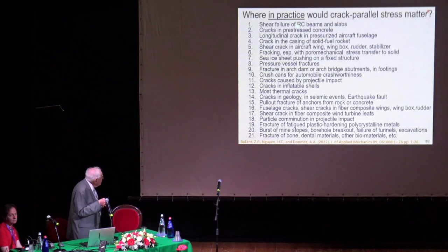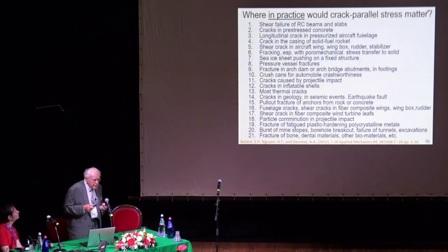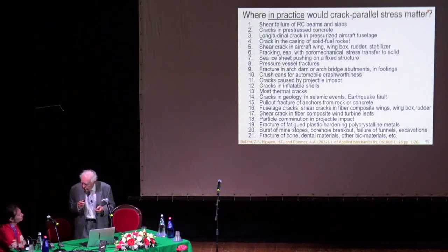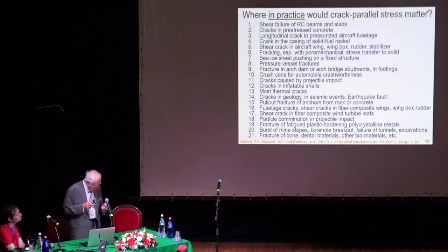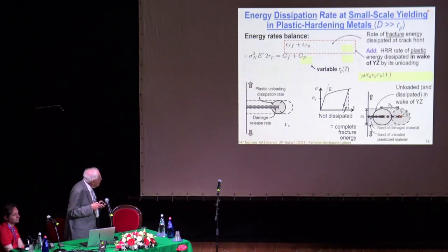I will not go through all this. This is listed in a paper published several weeks ago: shear failure of reinforced concrete beams, pressurized fuselage, casing of solid fuel rockets, and so forth. These almost always involve significant stress parallel to the crack. Rare are the cases with zero stress parallel to the crack, although all the existing fracture specimens that we have have essentially zero crack-parallel stress. So this has actually been misleading information.